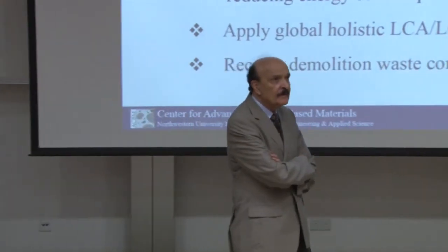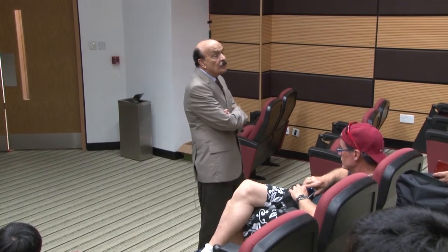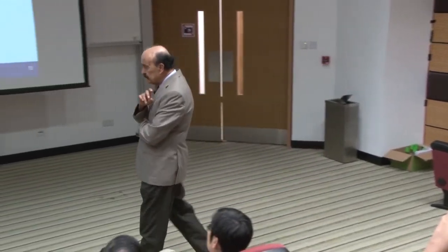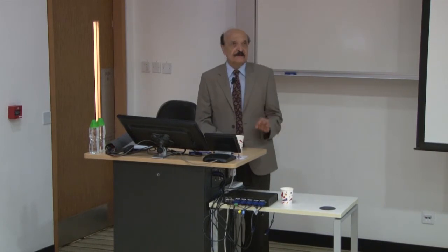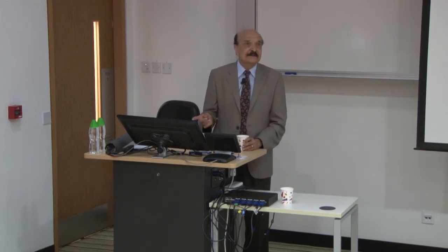Yes. Thank you very much for the talk. I have two questions. One is, you mentioned the utilization of nano-alumina. As we all know, alumina has shear thickening properties. So what is the effect of utilization of nano-alumina on rheology? First of all, that's a very important point. When you add nanoparticles, because they have a large surface area, rheology becomes very important. And the trick is you add as little as possible. So as you saw, 0.25% nano-alumina on cement. But certainly rheology is also important with many other nanoparticles.